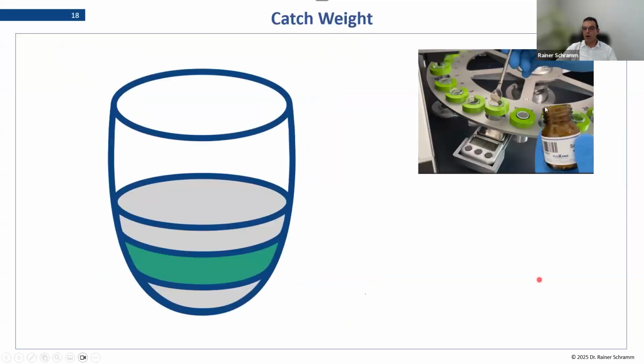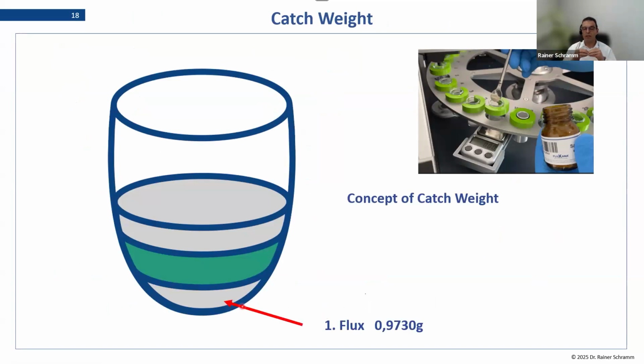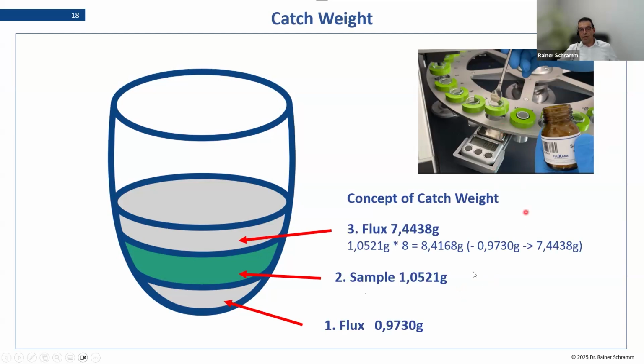So catch weight in our automatic system means that first we weigh a bit of flux, so that our sample is not really at the bottom of the crucible. And then in a second step, you put in sample, just roughly between 0.9 and 1.1 gram. So you use such a small balance just to estimate your amount of sample. And then when this is done, it is weighed on the precise balance again, and the software calculates how much flux you have to add so that your dilution factor is exactly 8 in the end.